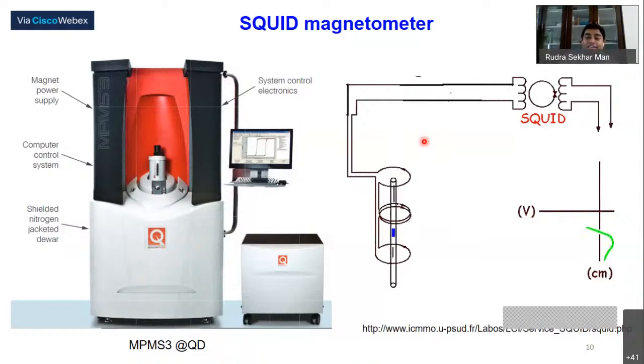So that means the sample also has to be kept inside the magnetic field in order to have the total magnetic field respond. The field at the center of the magnet is very high, not only high, it is also more homogeneous. So those things one has to take into account. So that is the typical measurement one takes. You put the sample inside, and then you have some kind of a variation within the magnetic field, and you get a signal. Then you try to analyze it.